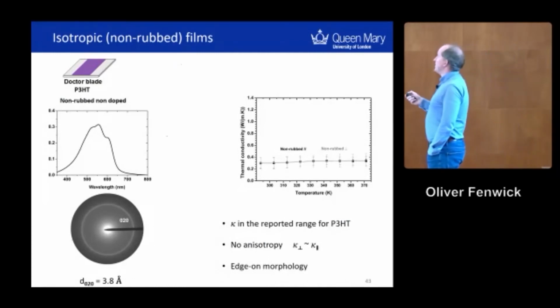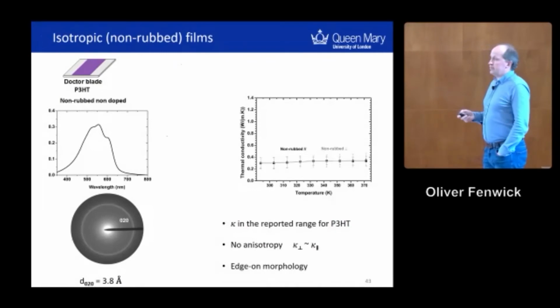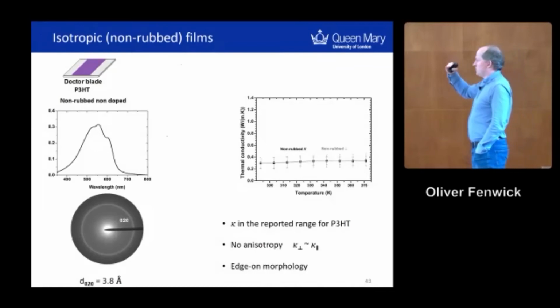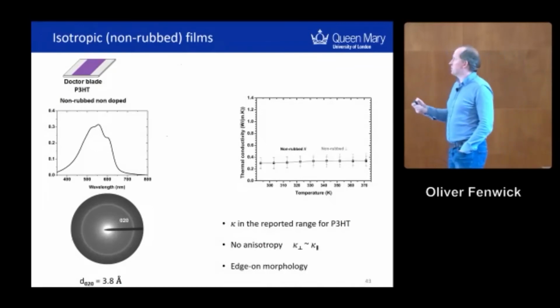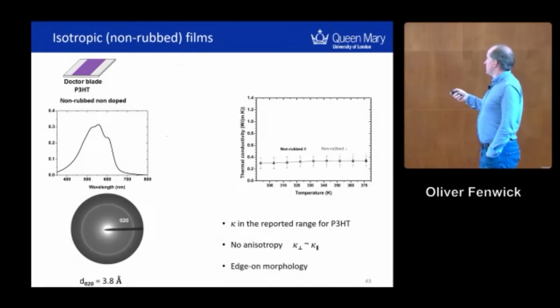But first of all, as a sanity check, this is just measurements of the unrubbed P3HT and not even doped. And we get the thermal conductivity of about 0.3 watts per meter Kelvin with an error bar. P3HT is typically 0.3 or a little bit below 0.3 watts per meter Kelvin. It's isotropic, of course, and it has an edge-on morphology.